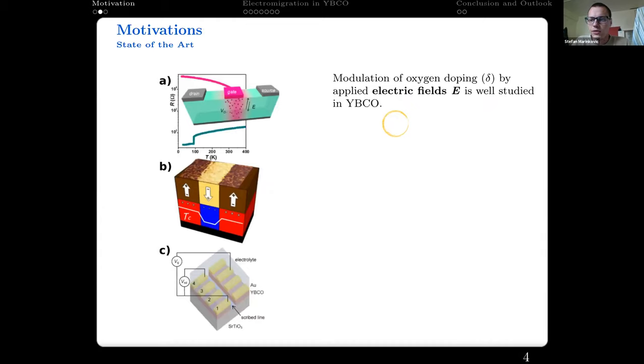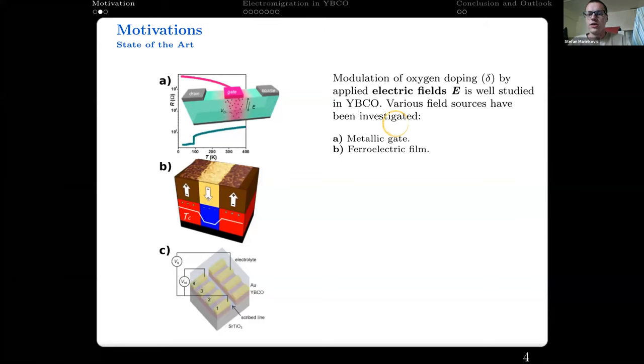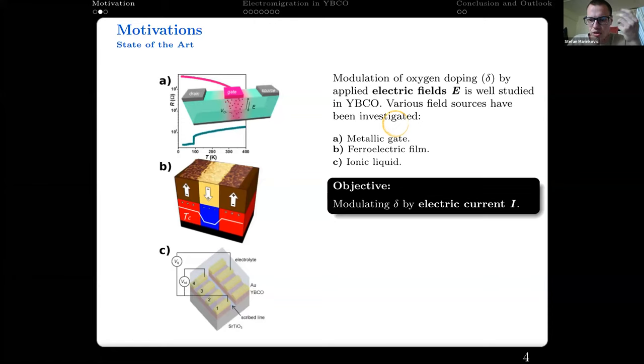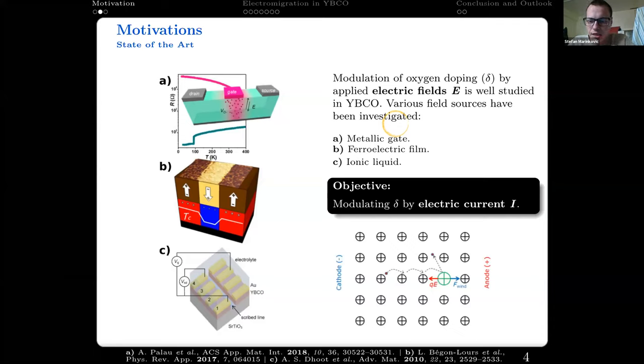We are motivated because it has been of interest to modulate the properties of YBCO, as discussed earlier, and it is well studied using electric fields, as in Palau's work, or using ferroelectric films, or even ionic liquids, as in the works of Begon-Lours in image B and Dhoot in image C. But we wanted to change this up a little and look at modulating by electrical current instead. This is possible due to electromigration, illustrated in this scheme, where an electron hits an atom and exerts a force that causes it to move, causing diffusion.